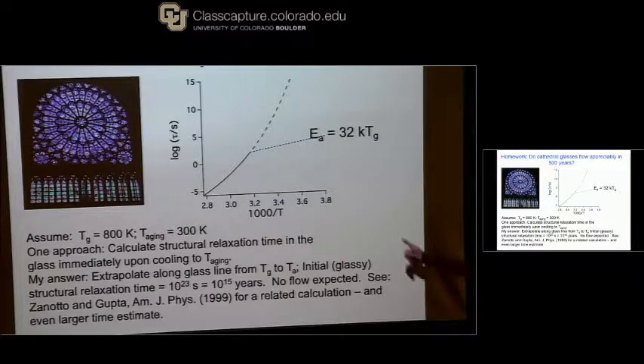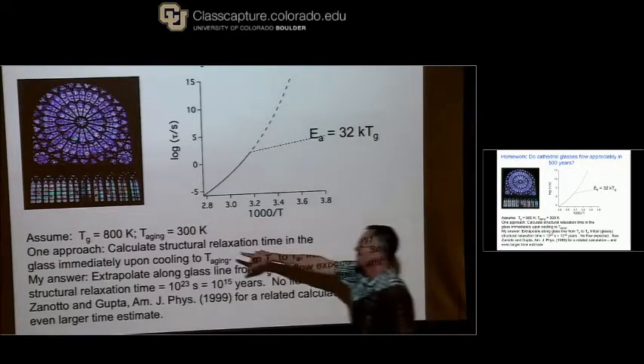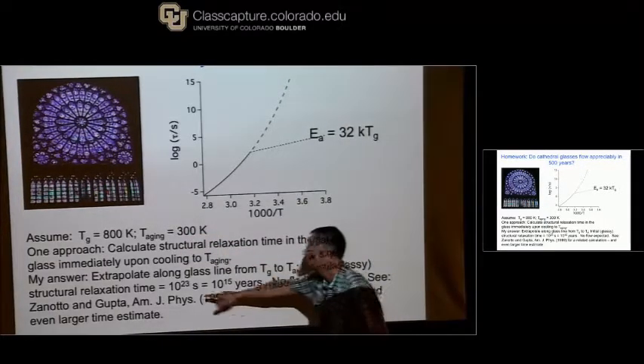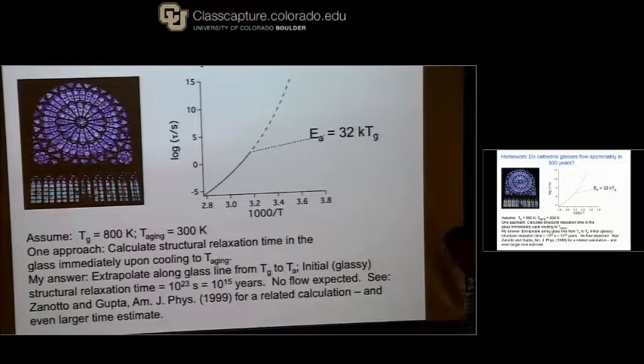So you just need to extrapolate way down in temperature, because you have to get all the way down to 300 Kelvin. And if you do that, you estimate not the equilibrium structural relaxation time, but the initial structural relaxation time of the just quenched material at 10 to the 23 seconds. Really big number. So it's not going to flow. If you're interested in a more detailed calculation, I refer you to this reference, which is basically the same calculation.